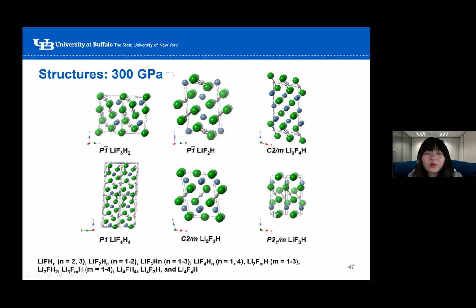There are shared structural motifs, that's interesting. For example, there are linear symmetric bifluoride anions in the lithium F2H structure, and it's also found in lithium 3F4H and lithium 2F3H. There are also nonlinear asymmetric bifluoride anions that are found in lithium F2H, lithium F4H4. And the bifluoride anion is very interesting in lithium F3H because it's linear but asymmetric.